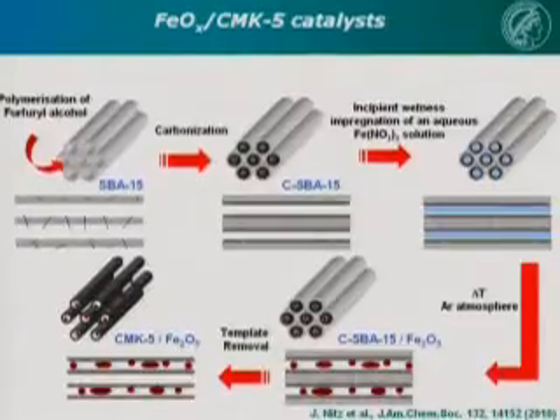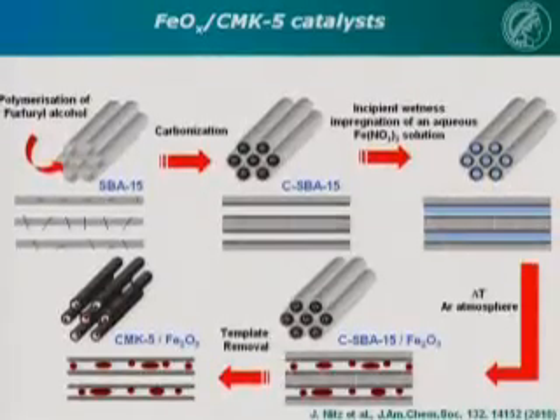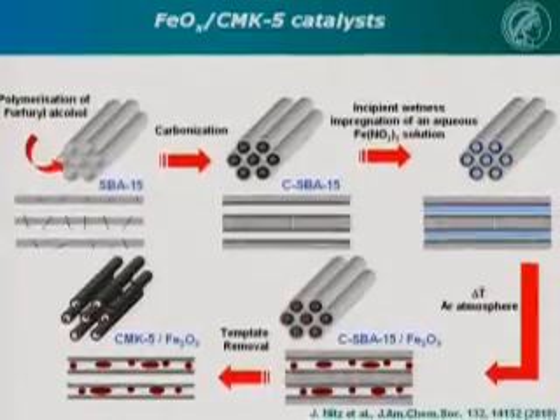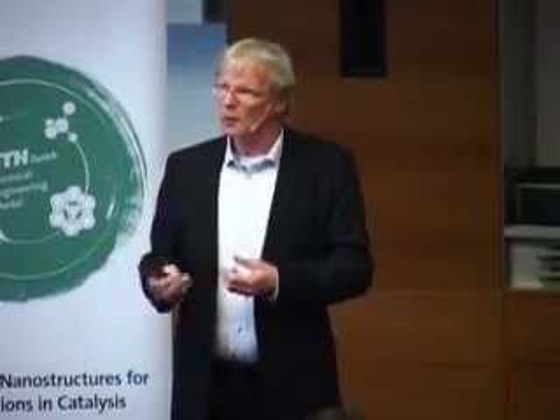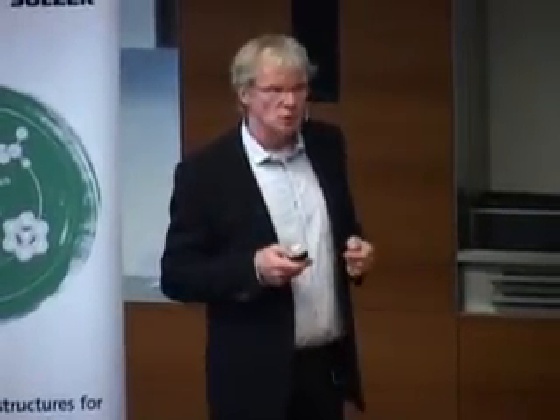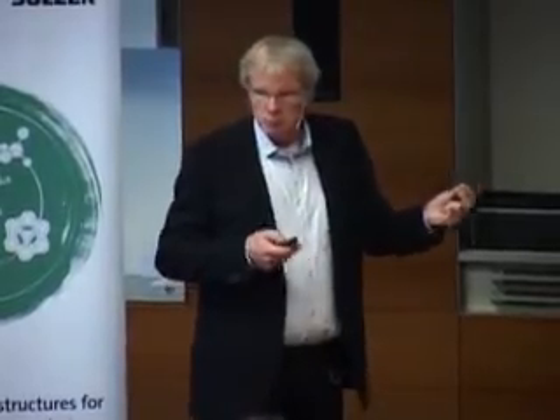This has been done by Joachim Nitz, and the target was to produce a catalyst for ammonia decomposition. There are discussions that ammonia could be, at least in niche applications, a very good storage compound for hydrogen. Because if you decompose ammonia, the products are nitrogen and hydrogen, so it's a very clean hydrogen without any catalyst poisons. So if you have a good way of decomposing ammonia, this could be used to release hydrogen when you want it in a clean form. And iron is known to be the basis for the ammonia synthesis catalyst. So iron compounds should also, by microscopic reversibility, be good catalysts for ammonia decomposition.